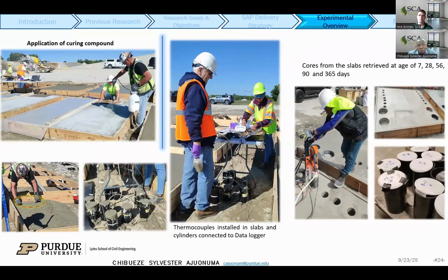And also for each of the slabs, before the concrete for the slabs was poured, they were instrumented with thermocouples, so that we can evaluate the temperature of the concrete mix over time. And at each of the testing ages, 7, 28, 56, 90, 365 days, cores were extracted from the slabs and brought into the research laboratory and tested.